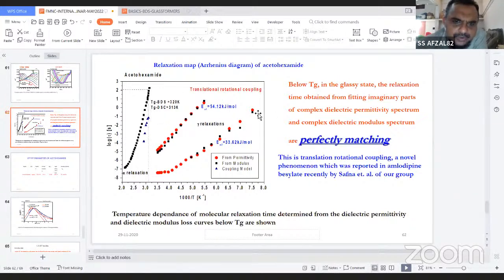So in the glassy state, you can see the data, the points are from the permittivity representation and from the modulus representation. That means I have calculated the time from the modulus spectra as well as from the permittivity spectra. And then I plotted in this Arrhenius diagram. I found that these are matching, these are corresponding, and that means both the representations represent the relaxation from the same origin. So that means this is a process called translation rotational coupling, because the modulus representation is basically